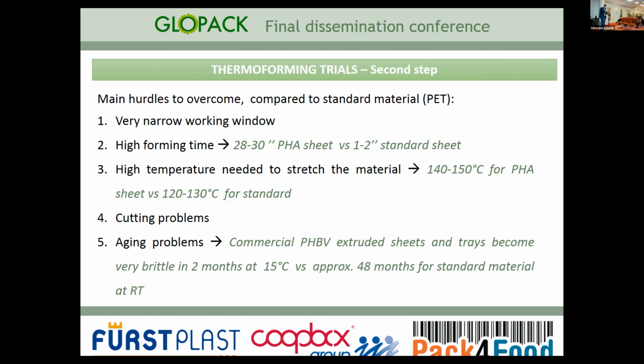After the first test, we also produced trays that were used afterwards for the shelf life test. We found different issues in the thermoforming of this commercial PHBV material. The first one, as was also said before, is a very narrow working window. This means that in thermoforming, usually you can work on time and temperature. But if you go outside the good working window, which is very narrow, you can have two problems.